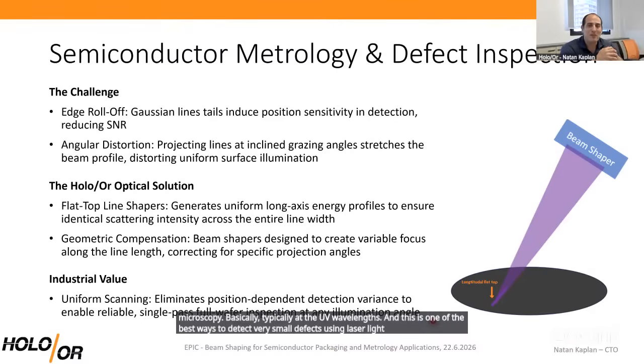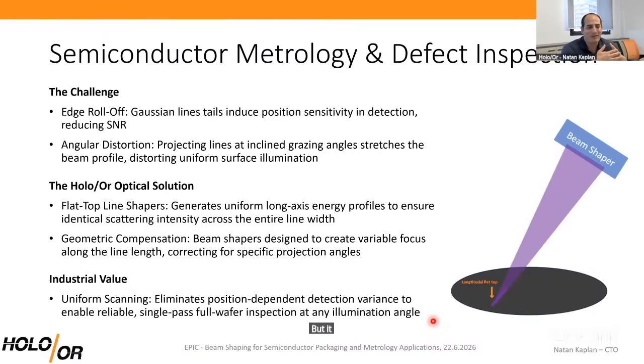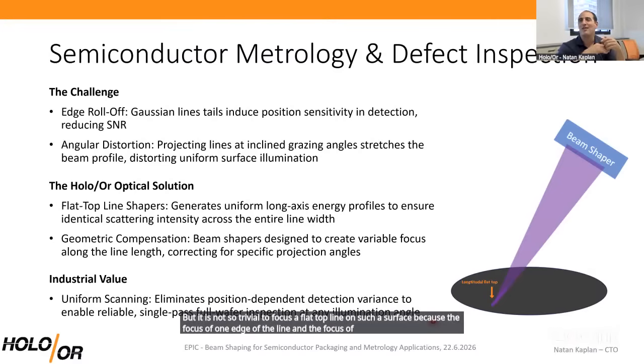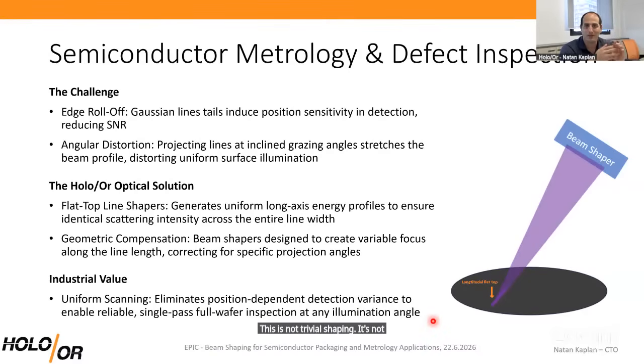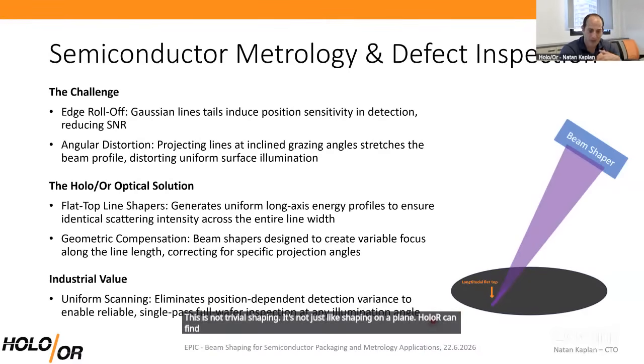And the problem is that, of course, you want a uniform signal. You want a flat top intensity along your line so that any defect will generate the same signal and the system has a good dynamic range. But it is not so trivial to focus a flat top line on such a surface because the focus of one edge of the line and the focus of the other edge of the line can have a difference in depth of focus of several millimeters, while the line's thickness is often several tens of microns. This is not trivial shaping. It's not just like shaping on a plane. HoloOr can find a solution for that, and we have solutions for that.